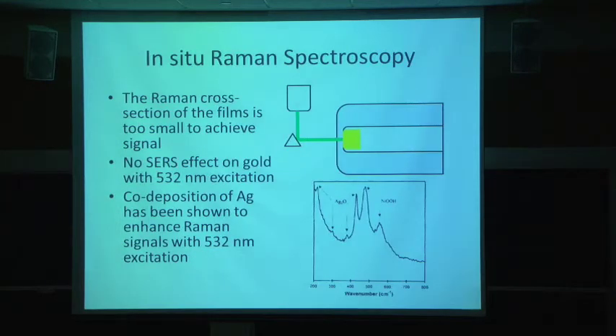Okay, so our experimental setup looks something like this. We have a green laser that comes out of a microscope. It hits a mirror and goes sideways into an electrochemical cell. We have a gold disc over here. We can deposit nickel oxide onto this gold disc, and then we can do in situ Raman under electrochemical conditions. We have a green laser, so there's no SERS effect on gold. So we co-deposit silver in here, and you'll see some evidence of silver oxide peaks forming, but that allows us to see the formation of these nickel oxyhydroxide forms.